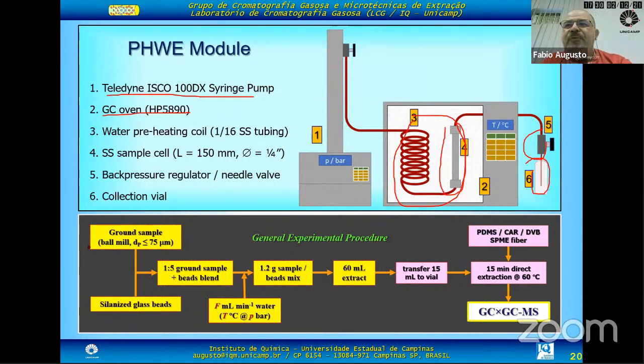Put your sample here. We grind the sample to very small particles and mix them with glass beads, in a 1 to 5 ratio. We cannot put the sample inside the cell directly and pass pressurized water through it, because the particles are too fine. If you put pressurized water over it, it turns into a cake, something that is almost not permeable. So you have to disperse it in silane or another device. In this case, we use glass beads to avoid the sample being very packed. We put 1.2 grams of this sample-bead mix.